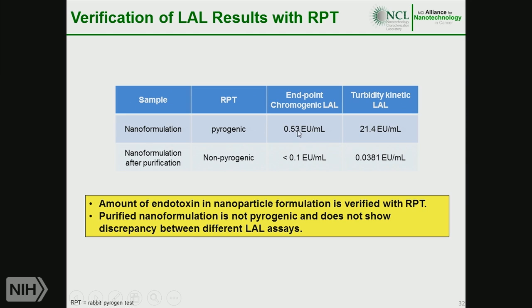And you see that one assay tells us that this formulation contains 0.5 endotoxin units per milliliter, and this assay shows us that we have 21 EU per milliliter. How do we know which one is correct? Inhibition enhancement control, which I showed you in the previous slide, was acceptable in both assays. We use a biological test to verify LAL findings, and this biological test is conducted in rabbits, and it's called a rabbit pyrogen test.